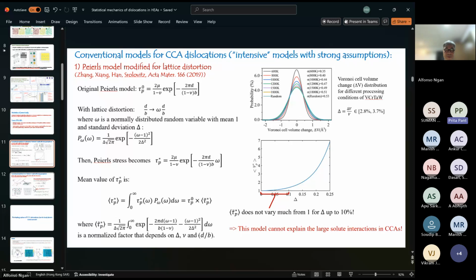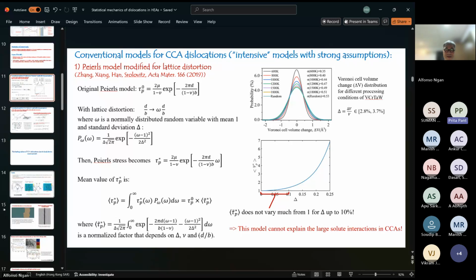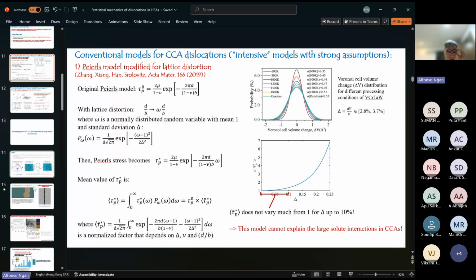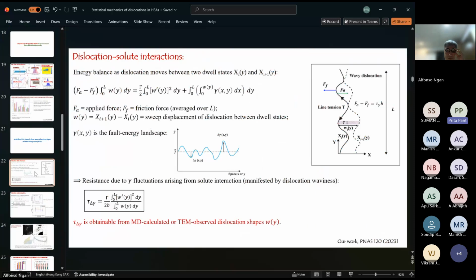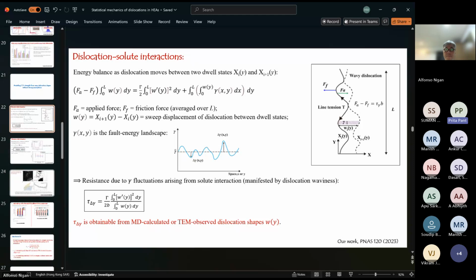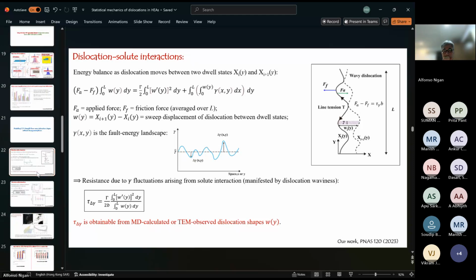I think I understood some parts of the talk. So I had a question about going back to that, where the dislocation is sort of fluctuating between states, the W parameter. I was wondering whether there would also be a temperature dependence to this shape that you get, and also time dependence. I mean, basically temperature and time, if you're saying that atoms segregate by diffusion. Well, diffusion, first of all, was not considered in this work. So in our MD, for that particular part of MD, we did not do the MC exchange. So we were not looking at dislocation-solute segregation. So the dislocation is moving in a static lattice, so to speak.